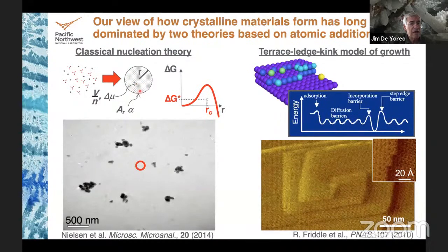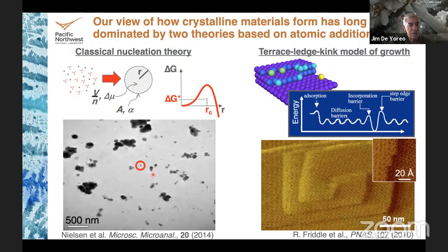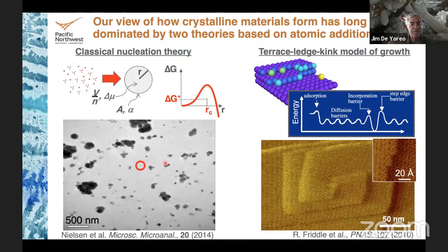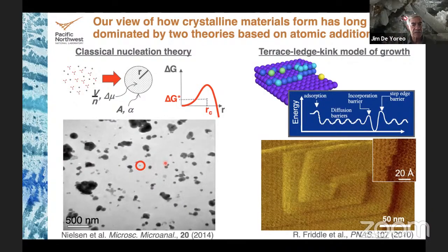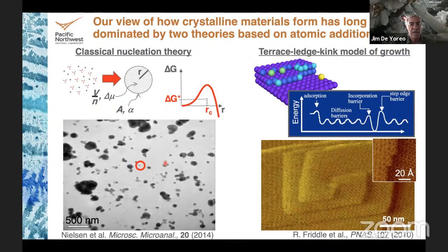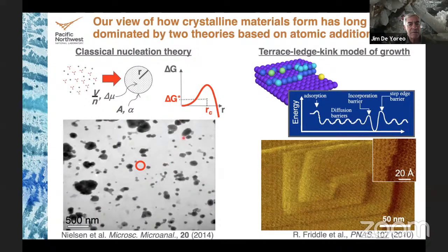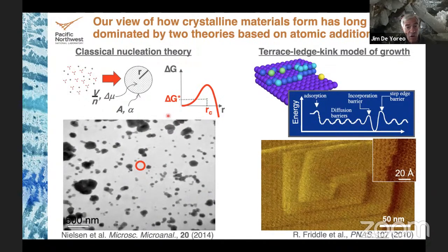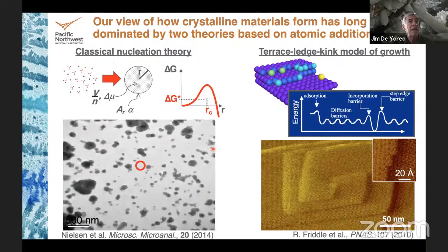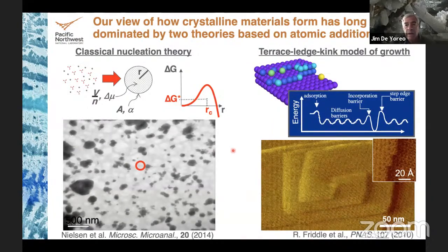And what's unique about this regime is that it requires the system to go uphill in free energy before growth can be spontaneous. And here's a nice in situ TEM movie showing the nucleation of gold particles. And in that circle, you can see a fluctuating particle that comes and goes and comes and goes, eventually disappears. And that's a reflection of the fact that it's trying to climb up this hill before it can spontaneously grow.